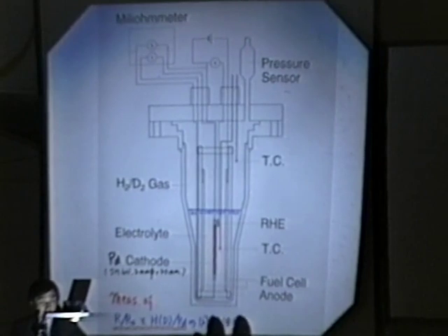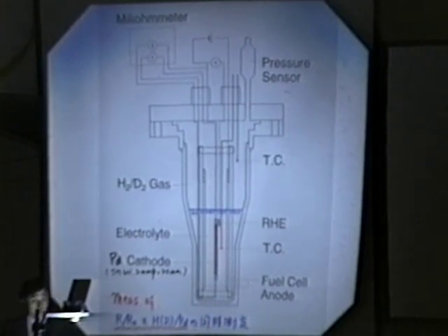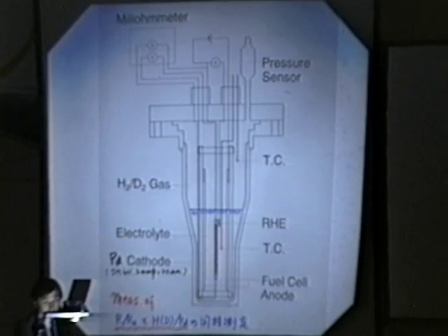So next, I'd like to remind you of the resistance measurement. But to do the resistance measurement, we should know the relation between the cathode loading and resistance. And so we tried to get this curve, which we call calibration curve, by conducting simultaneous measurement of resistivity change and also loading in our cell with fuel cell anode.